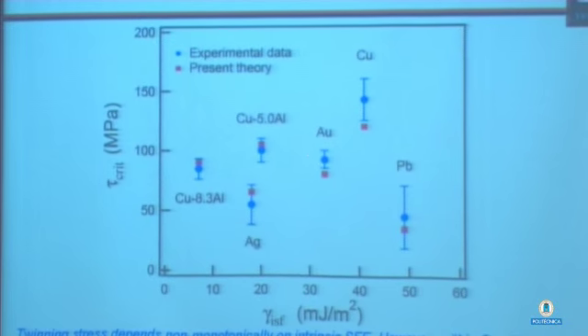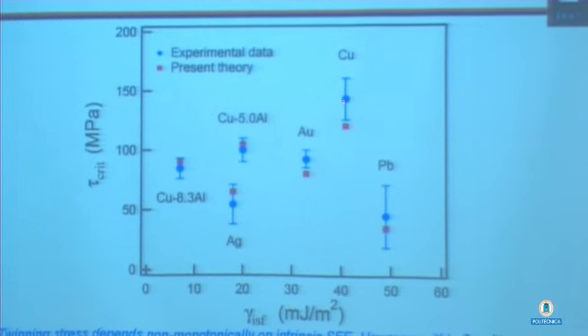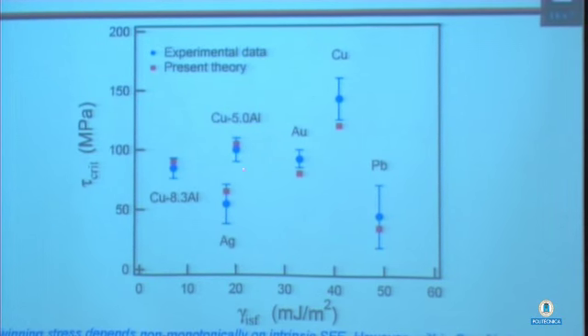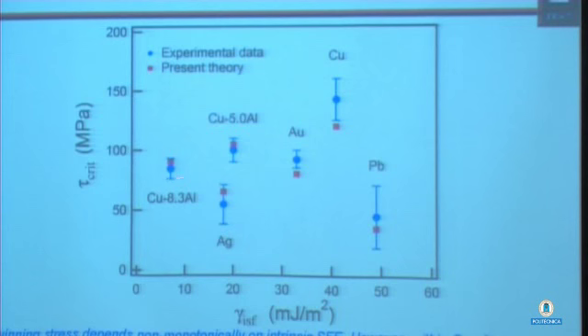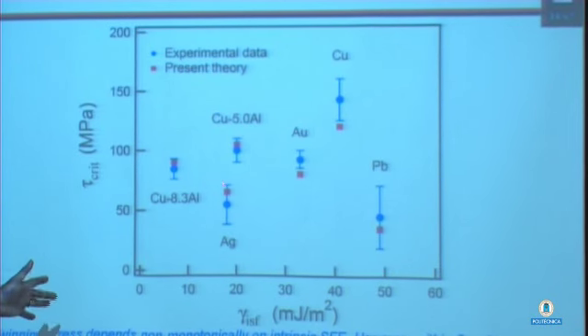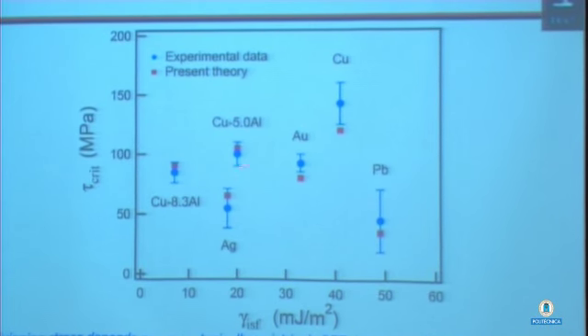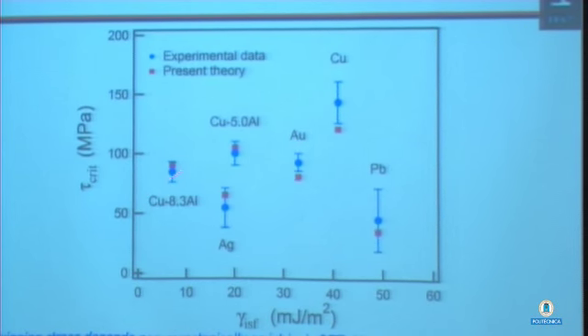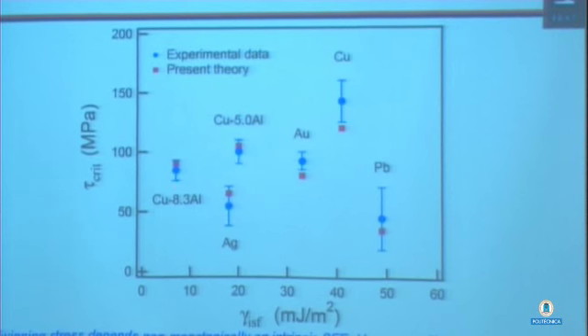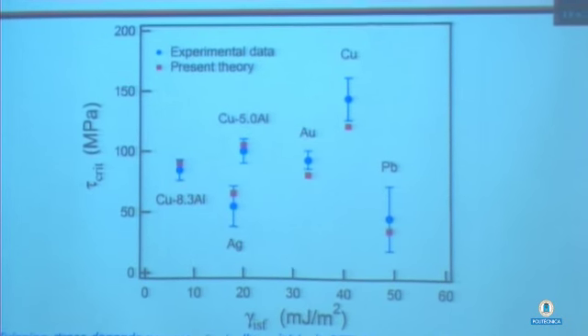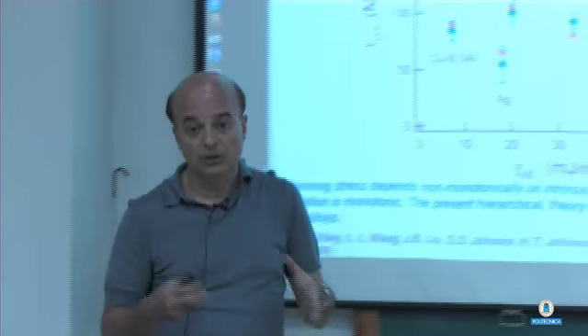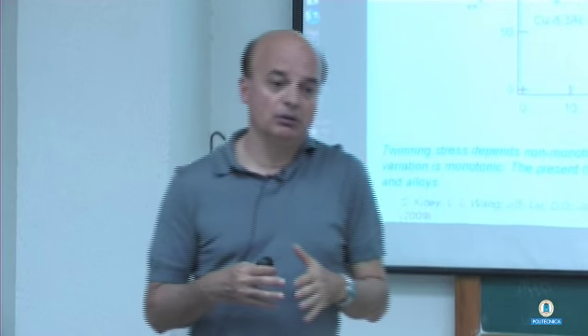And if you look at the results here for pure copper, 5% aluminum, 8.3% aluminum, these are again experiments done by others, and the predictions. You could see that the 8.3% alloy has a lower twinning stress compared to the pure copper. So a priori you wouldn't know that unless you do the calculations.